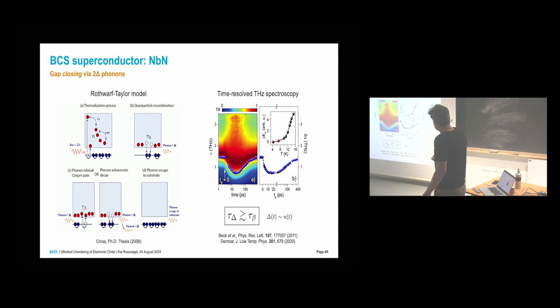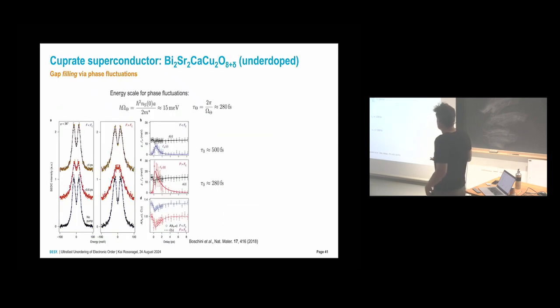People have measured this, and you can see how it quenches the gap size. In BCS type superconductors, it takes more than a picosecond to get rid of the electronic order. In cuprates, it's a little bit different because there again you have these phase fluctuations, and people have argued that by exciting those, you can fill in the gap. Again, here you nicely see in ARPES how you fill in the gap. The peaks stay more or less at the same position, but you quench the gap by filling it. And this can be a little bit faster because these phase fluctuations have a 15 millivolt energy scale, which corresponds to a time scale of 280 femtoseconds, and this then is the time scale of quenching the gap.